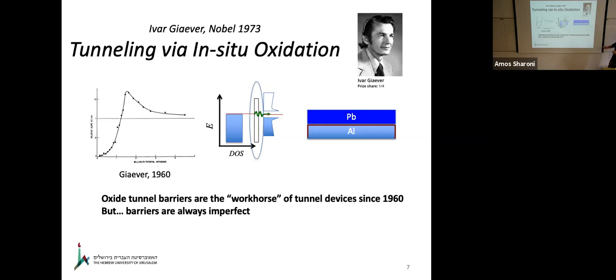And then what he did was deposit aluminum and lead. Lead is a superconductor below 7K. Aluminum is a superconductor below 1K, but at the temperatures that he measured, aluminum is a normal metal. So what he got is a structure which is very commonly used today. It's called a normal insulator superconductor junction. And essentially what you have here is a superconductor, it has this energy gap. That's a very prominent part of superconductor physics.